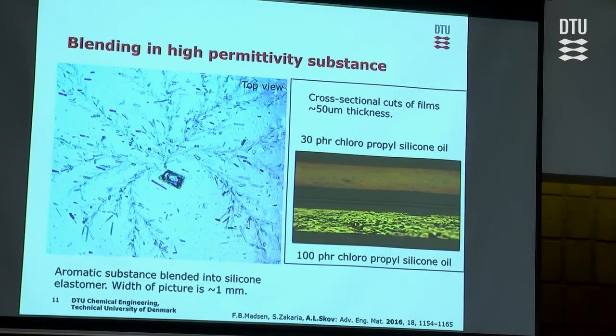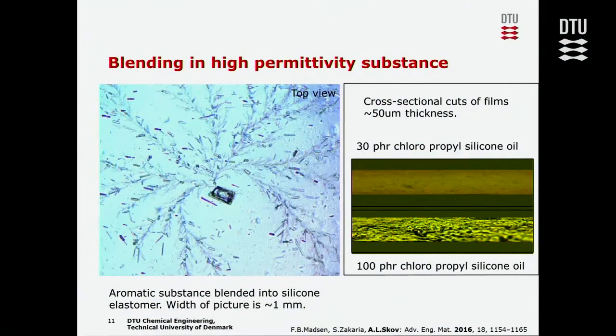Blending in high permittivity substances sounds really, really easy, but it's very complicated, because silicone polymers don't really like any other materials, more or less. So here we have just added an aromatic substance into the silicone. We speed mixed it. Usually that's sufficient to make sure they are homogeneously mixed. But then after casting it, it was obvious. It's actually a picture you can see with the naked eye, that we had this kind of phase separation. Of course, when you see it on this scale, you get a clear indication of how bad it is.